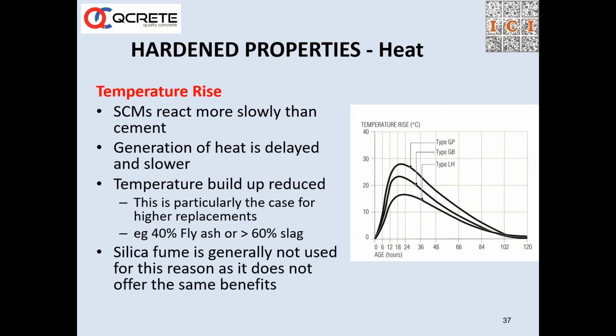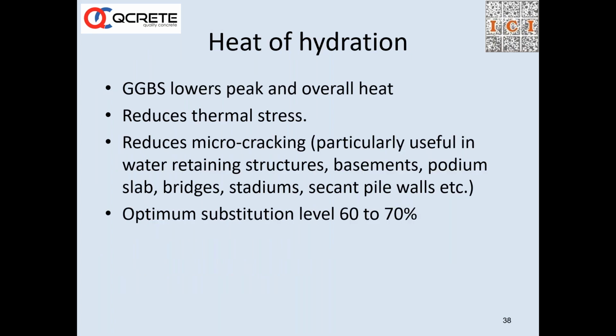So temperature rise is less when you are using GGBS or fly ash. GGBS lowers peak and overall heat, reduces thermal stress, reduces micro cracking. Optimum substitution is 60 to 70%. You know, the IS code permits usage of GGBS between 25 to 70%. But there are many people in India, many projects where they use 10%,